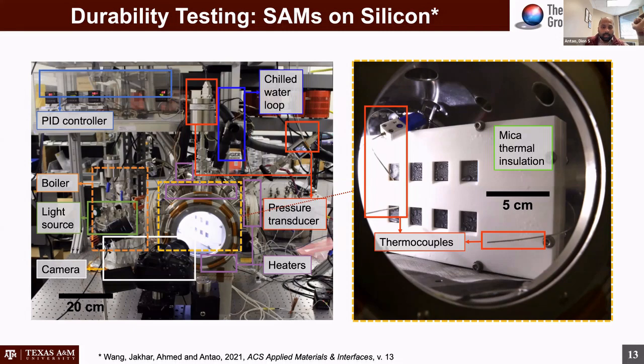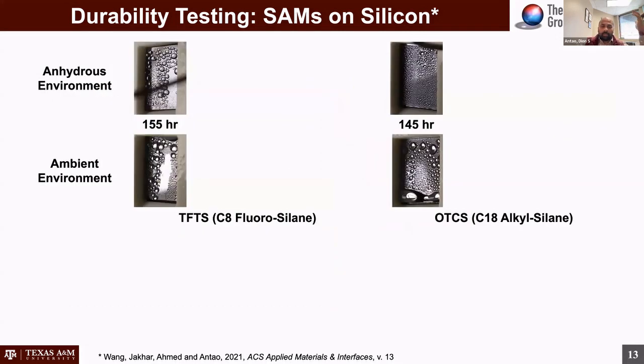And then we put the silicon coated samples in the system. We did 4 sets of runs in the sense that we have an anhydrous environment coating with an alkyl silane and a fluorosilane. And then we have the ambient or uncontrolled environment with a fluorosilane and alkyl silane too. And what we noticed was that right up to about 150 hours, there's no change in behavior on these surfaces. And we expect that because silanes will bond well with silicon.